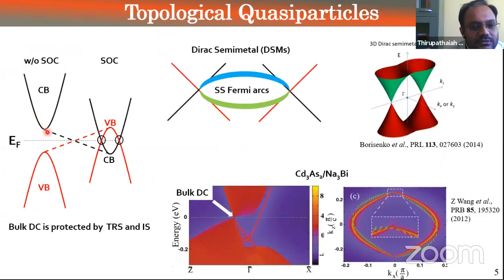Okay, now going back to the previous condition, again the conduction band is there, and the valence band is here. Now these crossing points are being protected by symmetries. In such a case you end up with a Dirac semi-metal, and here are two Dirac points in one Brillouin zone, connected by these surface Fermi arcs. Different colors represent different spin orientations. They look like this along the kz direction. This is the kz axis, this is the kx, ky axis, and this is energy. Here, these Dirac points are protected by two symmetries, time reversal symmetry and inversion symmetry. This is the bulk Dirac point, and these are the surface states, which connect the bulk Dirac points. This is when you project them, and this is the spin orientation taken from this paper.